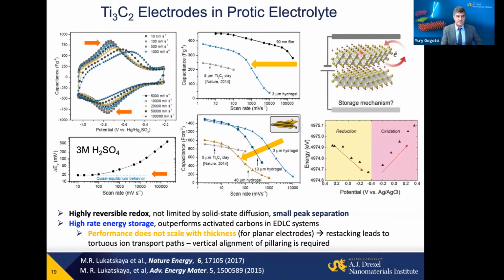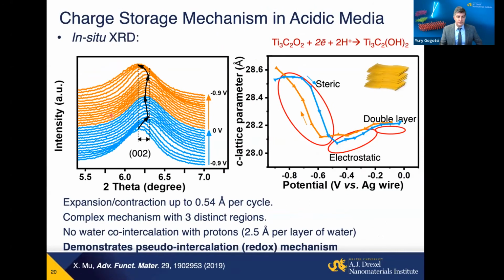What does it practically mean for us? It means that if we have materials with sufficient electronic conductivity, we should be able to design redox-based battery type energy storage devices that are capable of not minutes, but actually seconds, milliseconds even, charge storage using redox mechanisms. What we need are electronically and ionically conducting materials, and we need to design the architecture of electrodes, which will provide fast transport through thick electrode films. And in this case, we also can have transfer of electrons to and from transition metal atoms, which leads to a combination of this double layer and redox energy storage.